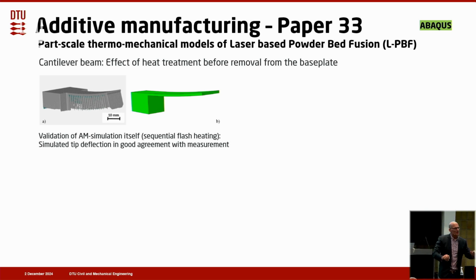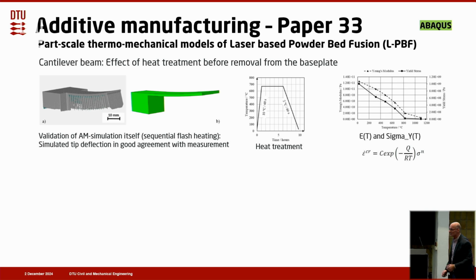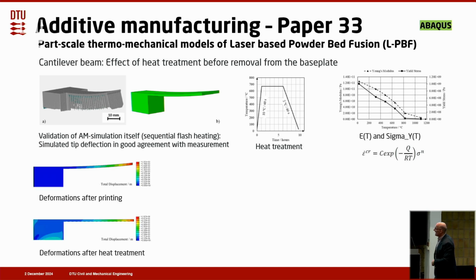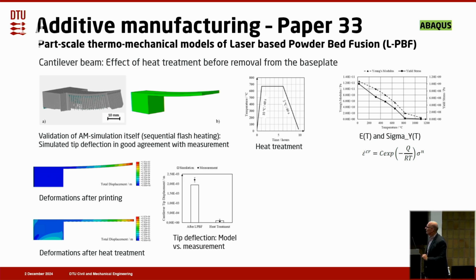And they were quite good, so we used that additive manufacturing simulation for taking and transporting the residual stresses into the heat treatment simulation. And the heat treatment profile looked like this, with these material properties. And these are the deformations after printing if you don't heat treat. And these are the deformations after heat treatment if you do. So we compared the tip deflection, this is after printing, and this is after heat treatment, and what you see here is the experimental finding, and we actually had a very nice agreement, and were able to predict that.